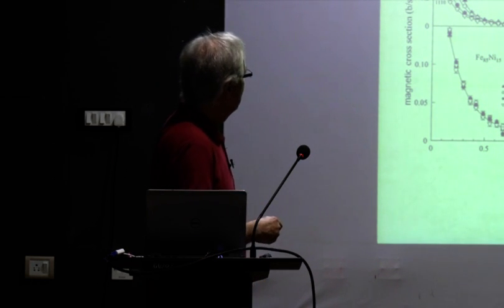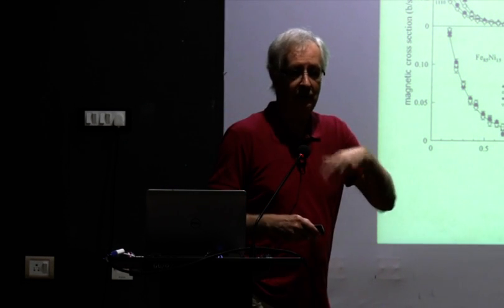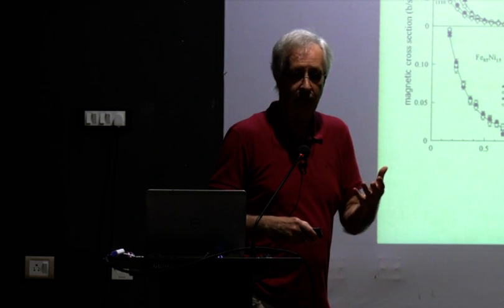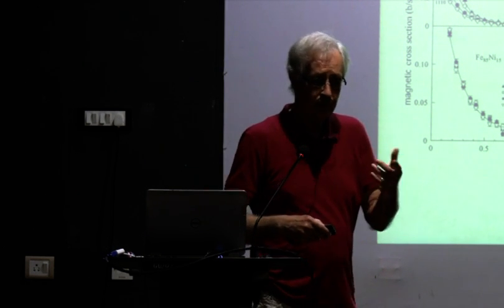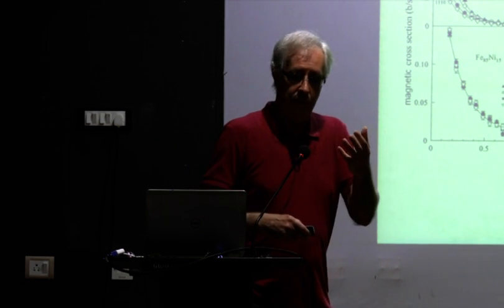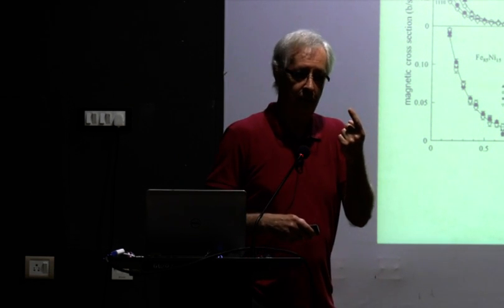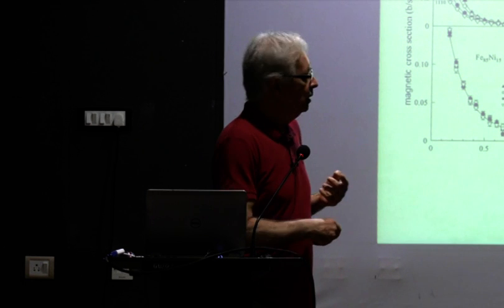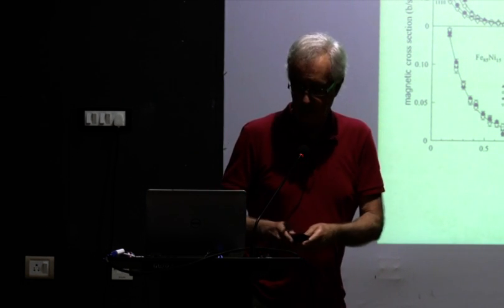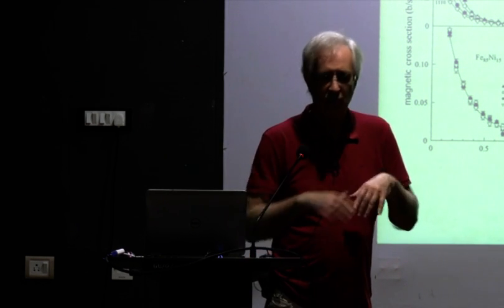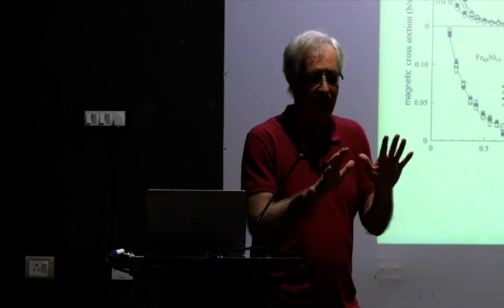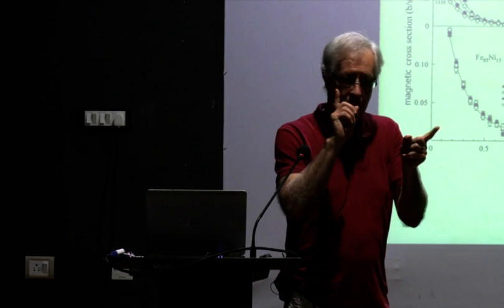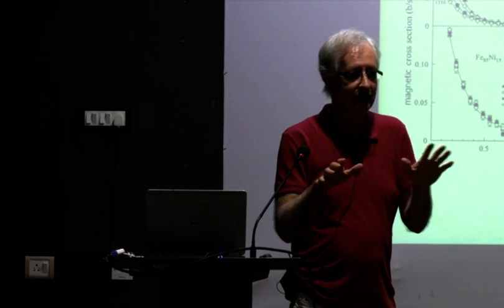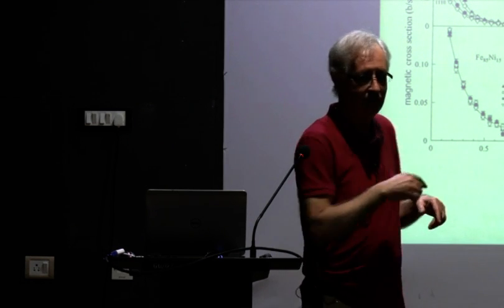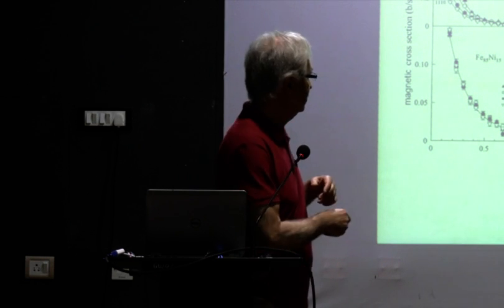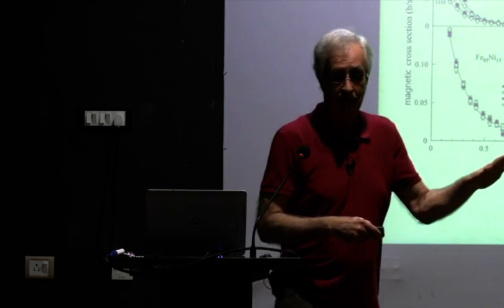Now, what do we see here? We see a forward scattering, okay? And what did we say yesterday? The forward scattering is an indication that we have ferromagnetic correlations. Just in between, I'd like to say that in a pure paramagnet where you would have pure local moments, which is very unlike the case in metals, above the Curie temperature your moments are disordered, period. That's finished. There are no correlations. The correlation length is nothing. So you wouldn't see forward scattering, you just see a straight line.